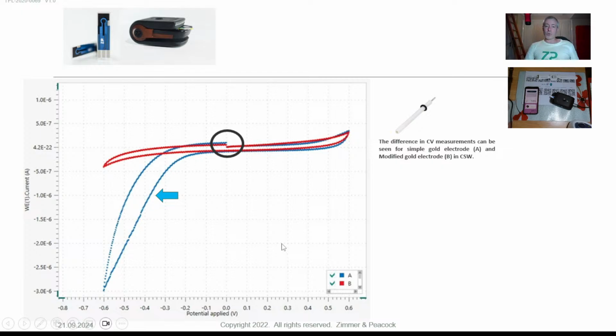This is going to become important in a bit, because all of your signals are actually the reduction of oxygen. That is what you're looking at. So you've got this gold electrode, you've got oxygen, and you're reducing it to get this kind of blue voltammetry. I didn't say what species you were forming, because that depends on the pH a little bit. So I didn't commit to that, and it doesn't really matter. For this discussion, it just means what you're seeing there is reduction of oxygen.